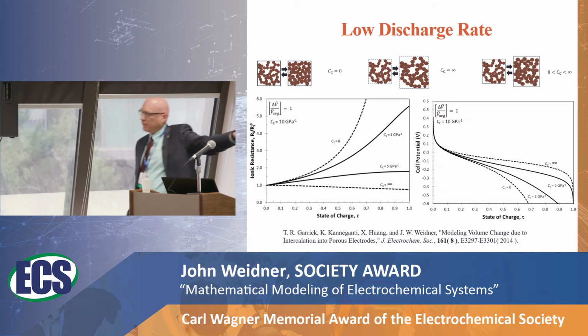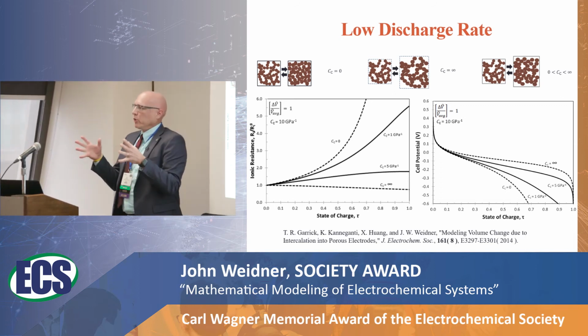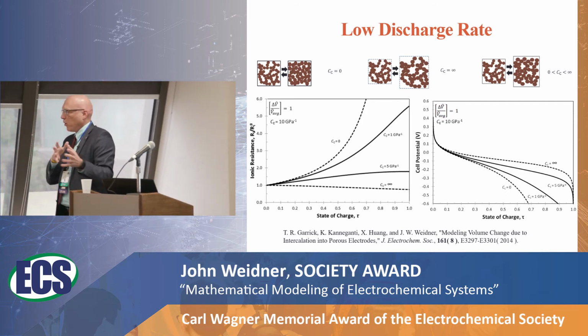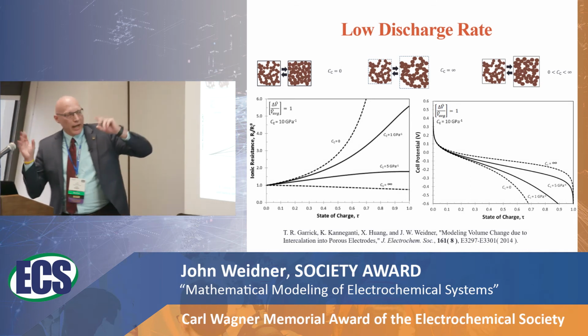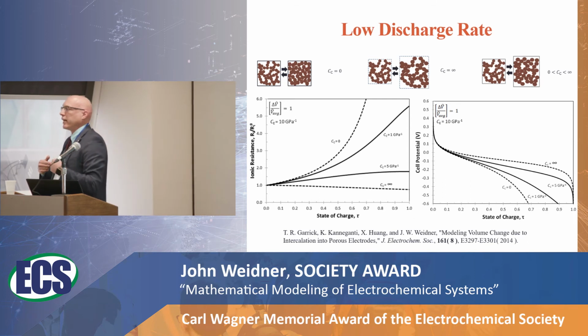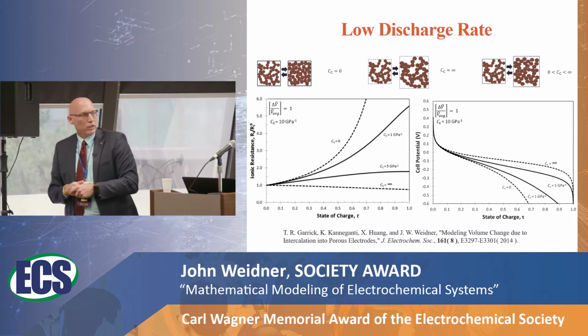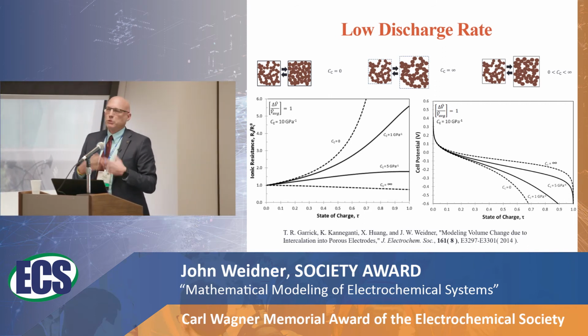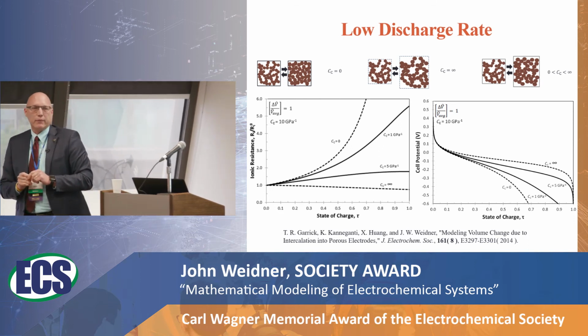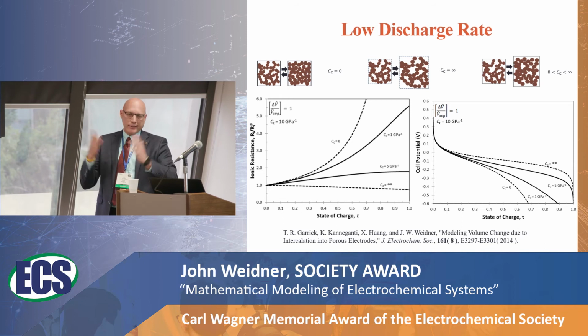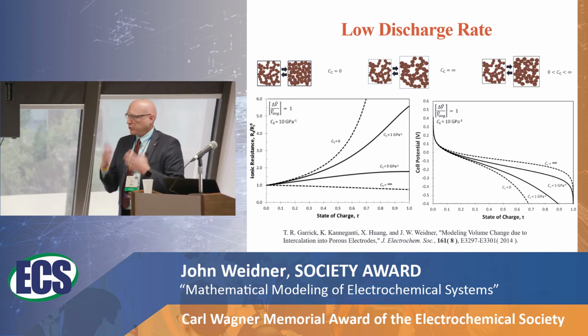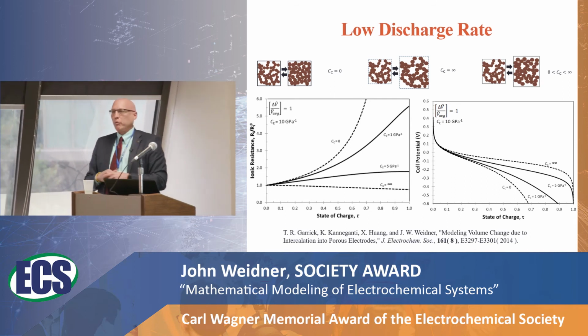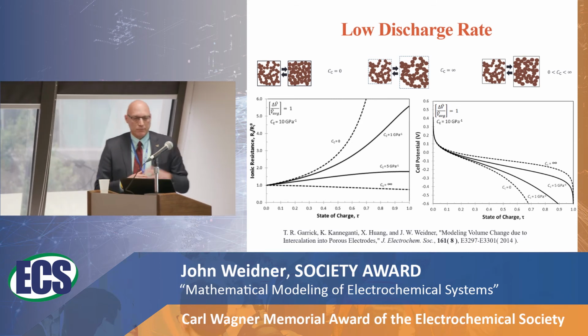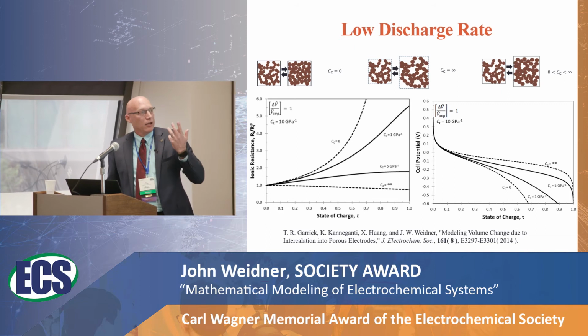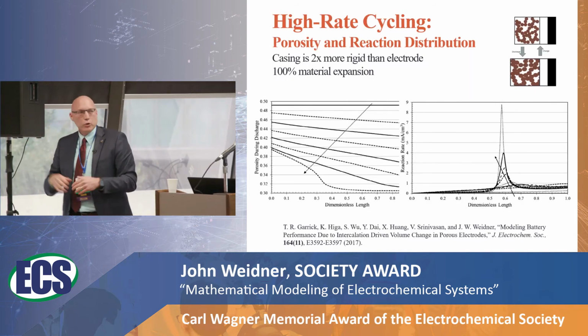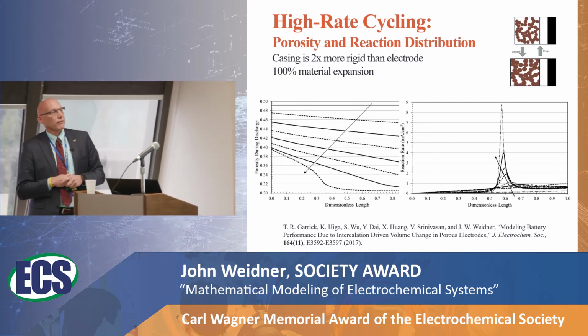And of course, this is actually more extreme than you would expect, because in a real battery, the anode is probably expanding and the cathode contracting and vice versa. So one is going to push against the other one, and here we didn't have that other case. But what we then did was put the equations that relate the expansion and the porosity into a real battery model. Taylor Garrick did a DOE fellowship out at Lawrence Berkeley Lab. They had a lithium-ion battery model with all the bells and whistles, transport and kinetics and so on. So we didn't have to reinvent that wheel, and Taylor put in the rock mechanics portion of it. Now we were able to extend it to not just these low-rate uniform fictitious electrodes, but to a real system.